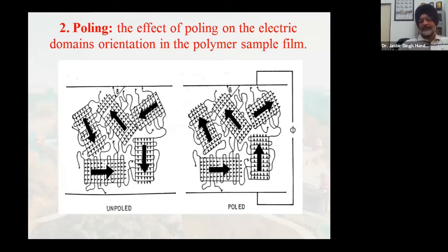Though dipole moment is there, there is self cancellation. But when you do poling, you find that all these dipoles, the net dipole moment, try to move. They start opening up and try to align in the direction of the field. Here the field has been applied, and we find that all the dipoles are trying to align in the direction of the field. They are better aligned, I would say. They are not ideally aligned. It is not the saturation polarization condition, but they are definitely better aligned in the direction of the field as compared to the first stage, where we have the unpoled film. So that is the effect of the poling.